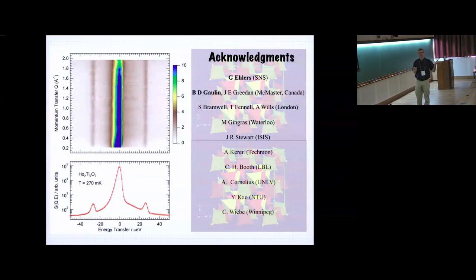We mentioned in NMR, you're looking at the nuclear spin. Heat capacity, if you go to the lowest temperatures, then there's been many mistakes in understanding heat capacity by ignoring the nuclear spin system. And in neutrons, we can also see it if you do the toughest of experiments. So in this pyrochlore spin ice, we found these two small peaks off to the side. Here they're shown, so the Q-independent peaks. This is energy. Just to make it look nice, it went that way.